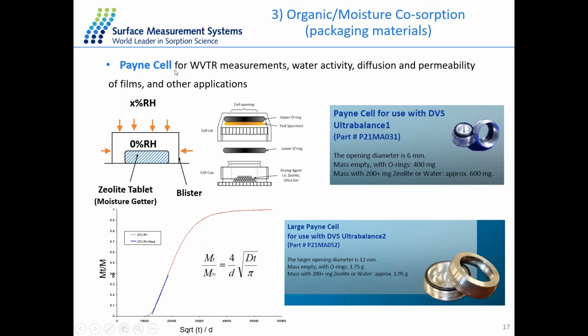So the Payne cell is an accessory you put in the middle of the sample pan, and then you can use this Payne cell to study the vapor transmission rate, water activity, diffusion or permeability for some thin film or some packaging material. So this Payne cell is composed of three different parts. The top of the cell, we have two different rubber O-rings here, and also the cup of the cell. And we can put the thin film sample in the middle of two rubber O-rings and seal the film with